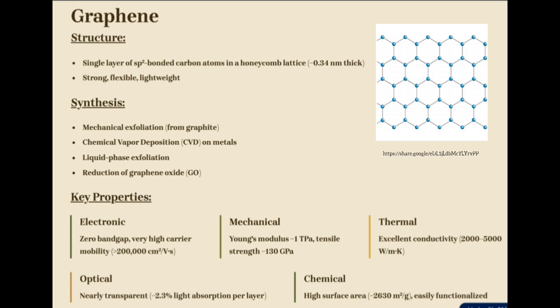It can be synthesized through mechanical exfoliation, chemical vapor deposition on a metal substrate, liquid phase exfoliation, or by reducing graphene oxide. Electronically, graphene has a zero band gap and extremely high carrier mobility, exceeding 200,000 centimeter square per volt second. However, the absence of a band gap limits its use in digital logic. Mechanically, graphene is one of the strongest known materials. It also exhibits exceptional thermal conductivity, making it attractive for thermal management.